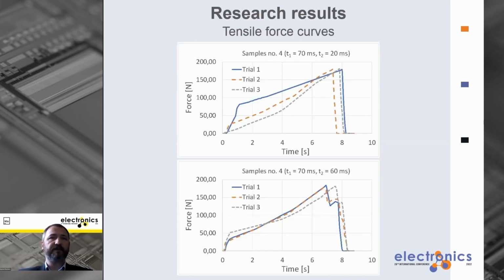So passing to the results. Each sample was subjected to a breakage test, a tensile test, and I remind that we had 3 trials for each time pulse. These are 3 trials. And the highest recorded force during breakage was taken into account. And so these points. And based on these 3 values, an arithmetic mean and a standard deviation were calculated for the analysis. Here we have only 2 representative examples of the tensile force curves chosen from many others.